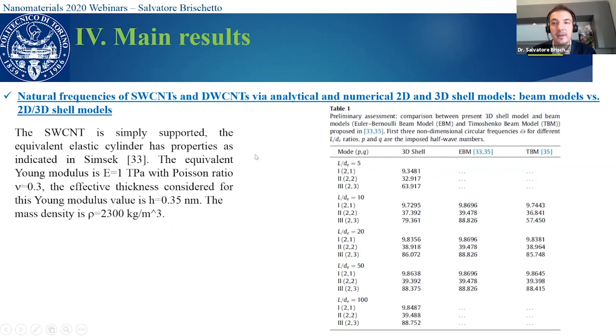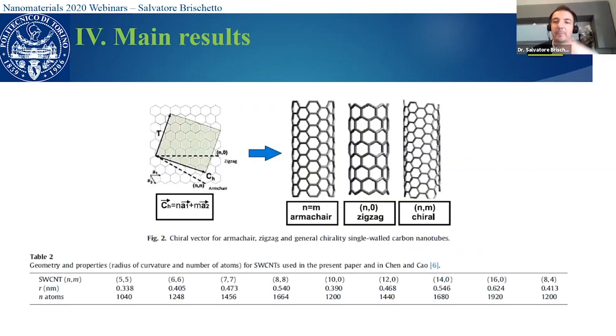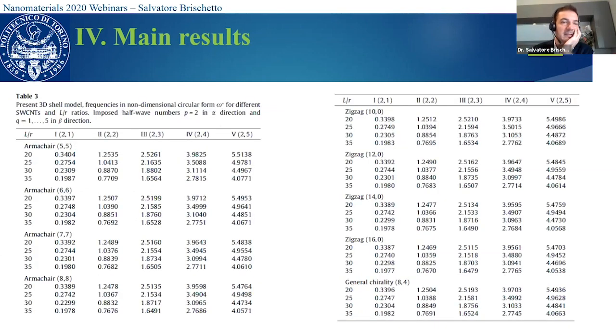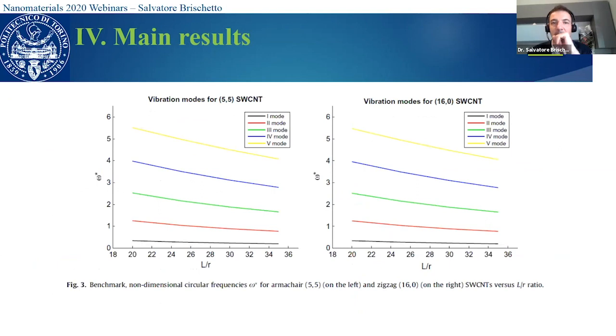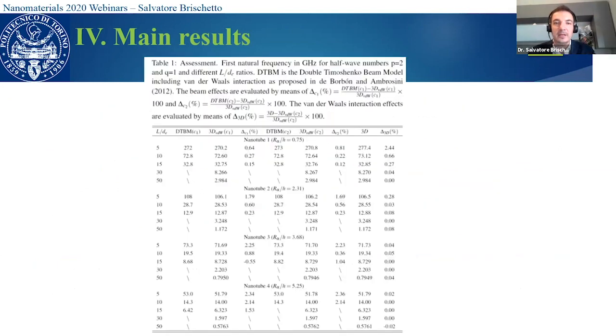Other results are obtained with the traditional model, and this is important because with the beam models, we can have results for moderately long and long carbon nanotubes, but when the carbon nanotubes are very, very short, we need a three-dimensional shell model. So we have performed several results about several chiral vectors, so for armchair, zigzag, and chiral nanotubes. These are not so important. We can see the different properties in terms of frequencies depending on the chiral vector and depending on the type of carbon nanotube. So the first, second, third mode, and so on.